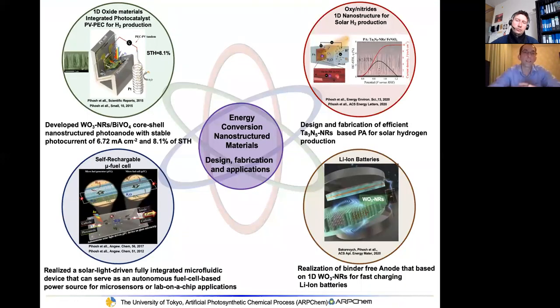Okay, so this is the last slide. So this is the conclusion. So we developed tungsten oxide nanorod bismuth vanadate core shell nanostructured photoanode with a stable photocurrent of around 6.7 milliamp and realized about 8.1% of solar to hydrogen conversion efficiency. So we designed and fabricated an efficient tantalum nitride Ta3N5 nanorod based photoanode for solar hydrogen production. And also we realized a solar light driven fully integrated microfluidic device that can serve as autonomous fuel cell based power source for microsensor or lab on a chip application.